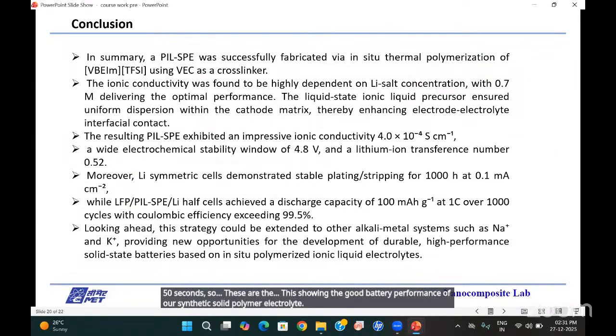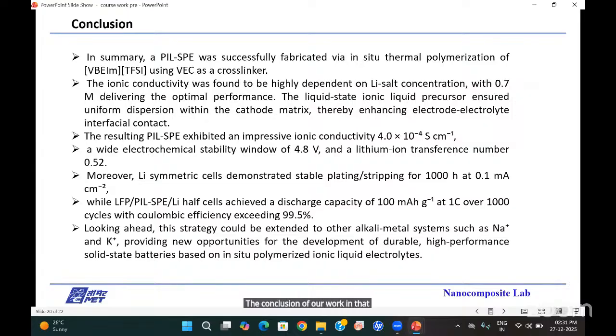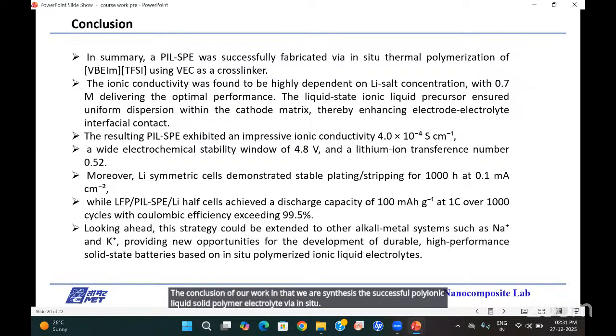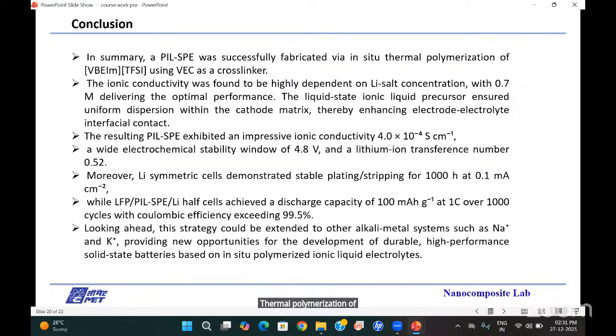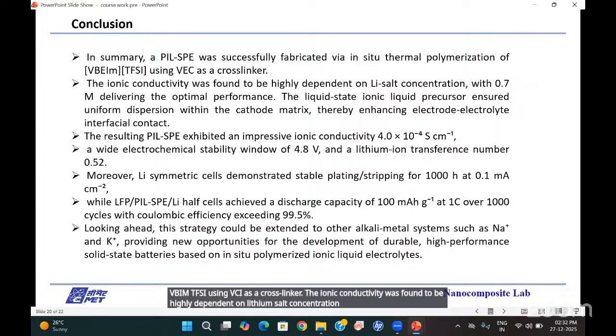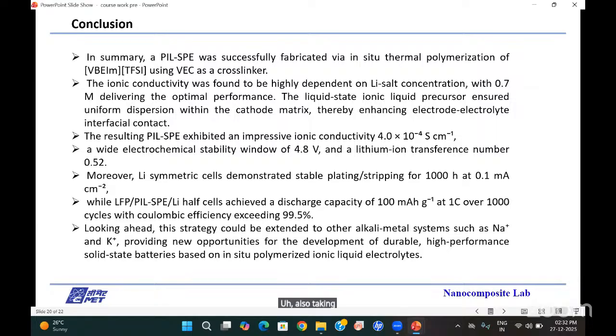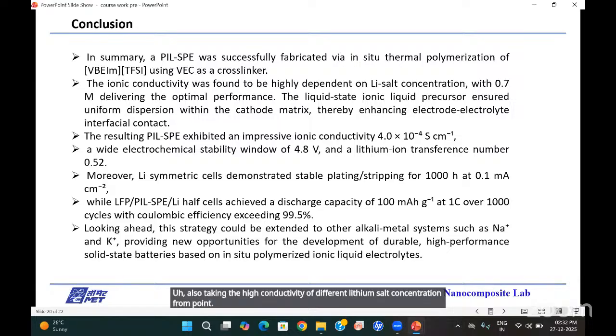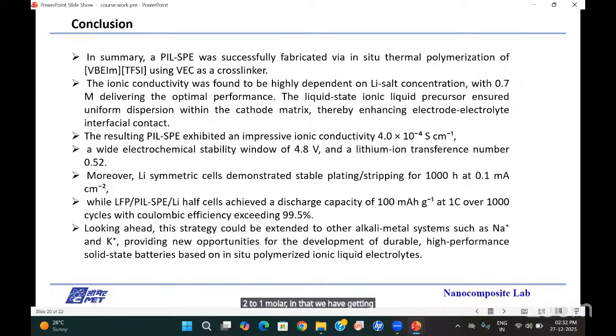The conclusion of our work is that we synthesized a successful polyionic liquid solid polymer electrolyte via in situ thermal polymerization of an ionic liquid, abbreviated as [VBEIm][TFSI], using VEC as a crosslinker. The ionic conductivity was found to be highly dependent on lithium salt concentration. We also measured the ionic conductivity at different lithium salt concentrations from 0.2 to 1 molar, and got the highest ionic conductivity at 0.7 molar, which delivered the highest optimal performance.